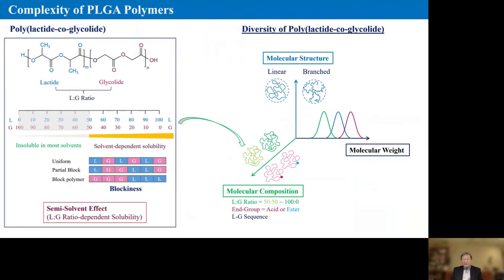Now, the complexity of formulation mainly comes from the complexity of the PLGA polymer itself. PLGA, as the name indicates, polylactide-co-glycolide, has two monomers, lactide monomers and glycolide monomers. So the ratio of lactide to glycolide, which we call simply LG ratio, determines the polymer properties. Most of the PLGAs we are using have a lactide content of 50% or higher, because if the lactide content is less than 50%, they do not dissolve in most organic solvents we use. So this LG ratio, and also the end group can be acid or ester. Not only that, lactide-glycolide sequence makes the polymer sometimes dissolve in the same solvent, sometimes it does not.